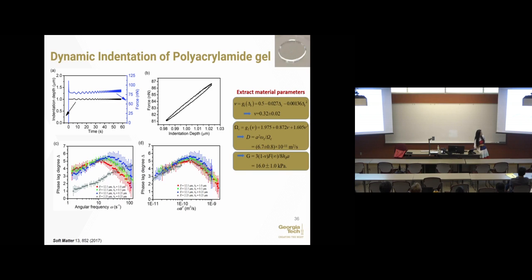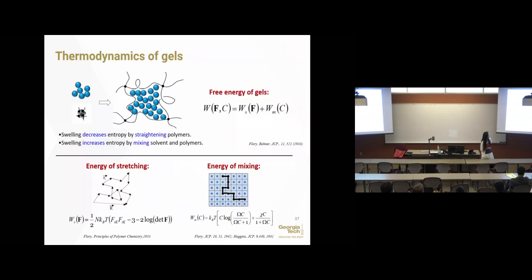And if we normalize it by a length scale squared, it collapses into one single curve, again confirming its poroelastic behavior, and we can easily use our formula to extract the material properties. So now the question is, how do we link the poroelastic property to thermodynamic properties of gels? For a simple neutral gel system,